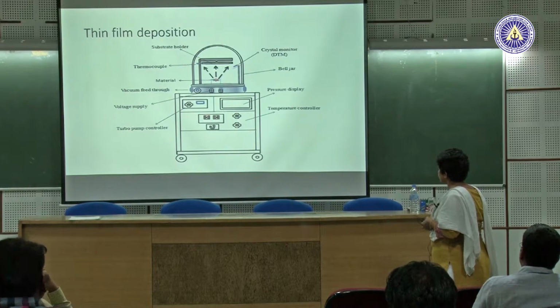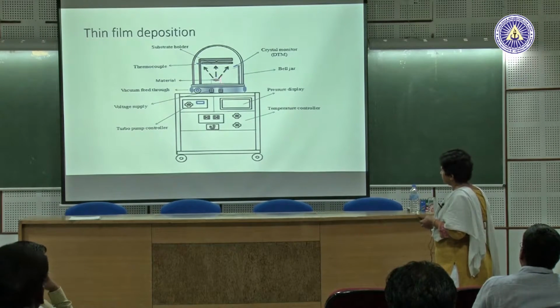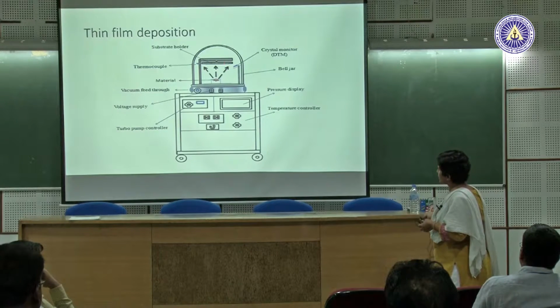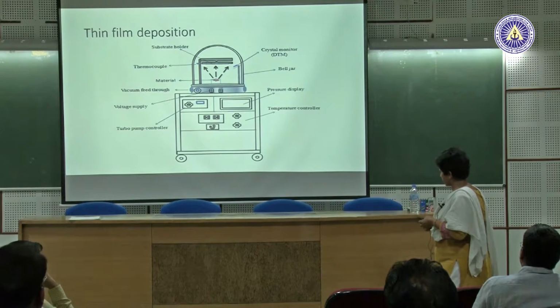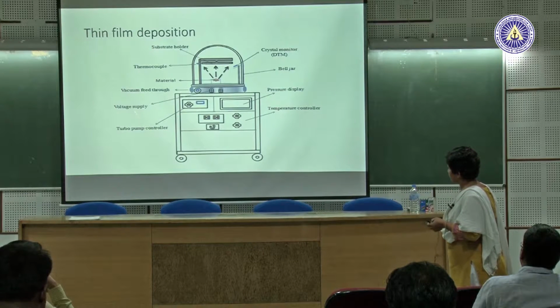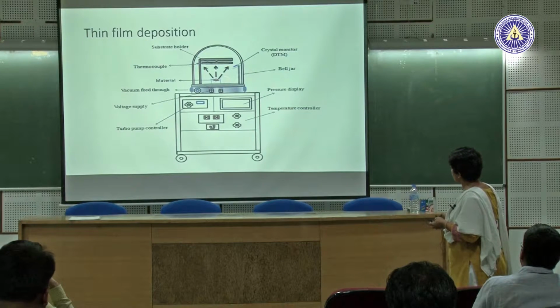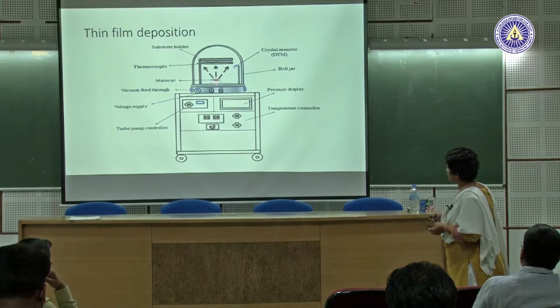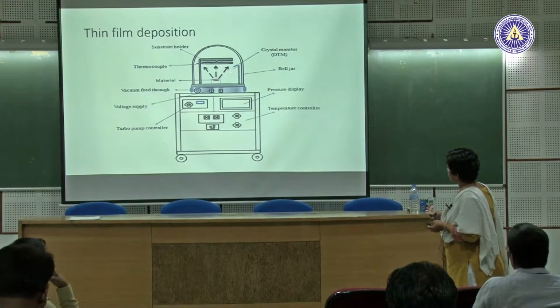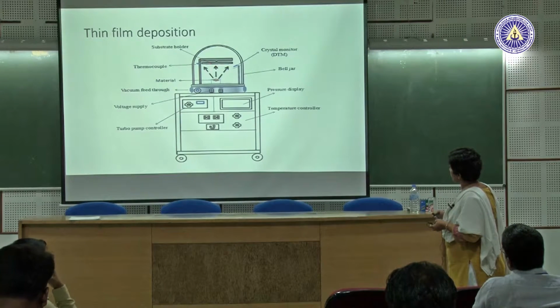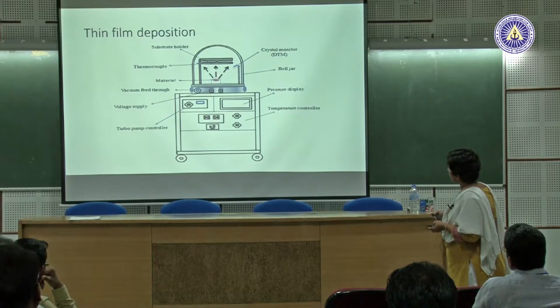So in a typical system, you would have vacuum, and it depends on your need and what kind of application you are doing, to what vacuum you take it down. So it will have pumps, the voltage supply, temperature controller. This is a thermal evaporator. The material is kept here. It is heated using resistive heating. The material gets evaporated and goes everywhere in the vapor phase. This is where I put my substrate holder. I monitor and can control the temperature of the substrate, and whatever vapor is being created gets deposited on this substrate.